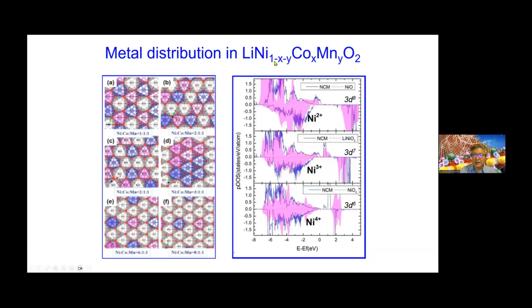So in this layered metal oxide, nickel, cobalt, manganese oxide layer, if we take one layer from the top view, the metal is coordinated by 6 oxygen atoms, and 3 of them are at the top of the layer, 3 of them at the bottom of the layer. Then in this octahedral configuration, they are neighboring hexagonal networks of metal atoms bonded by these oxygen atoms. So first, there are 3 metal elements randomly distributed with corresponding elemental ratios, this 111, 211, 611, 811, different ratios. And there are multiple atomic arrangements.